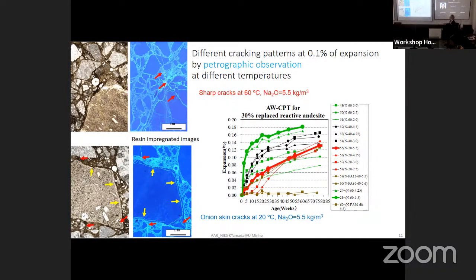This is very strange. And the red line indicates the test result at 20 degrees. Alkali content was modified from 2.5 to 5.5. Interestingly, at the lowest temperature with less alkali content, in the first half year, not so significant expansion was observed, but after that, rapid expansion was observed and exceeded other conditions. Low temperature and low alkali content exceed higher temperature and more alkali. This is very strange.